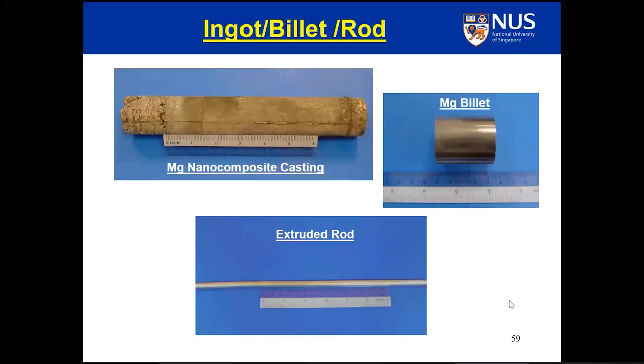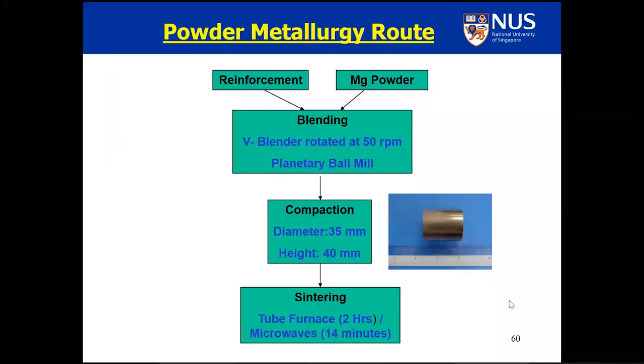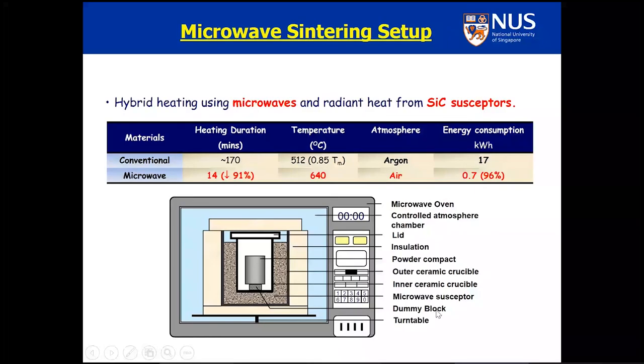Another way in which you make materials is the powder metallurgy route, in which you take the metal powder, or metal with the reinforcement, blend it, compact it, and then sinter it. Traditionally, people use a tube furnace to do the sintering, but we developed microwave sintering in our lab way back in 2004. Why do we use microwaves? These are the simple microwaves that you may have in your home. We just created a setup of a crucible outside, a crucible inside, a silicon carbide susceptor here, and we put the metallic billet in the center and close everything by insulation so that the temperature does not go out and spoil the electronics of the microwave.